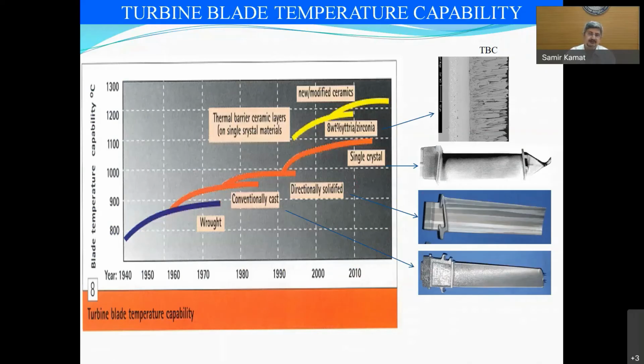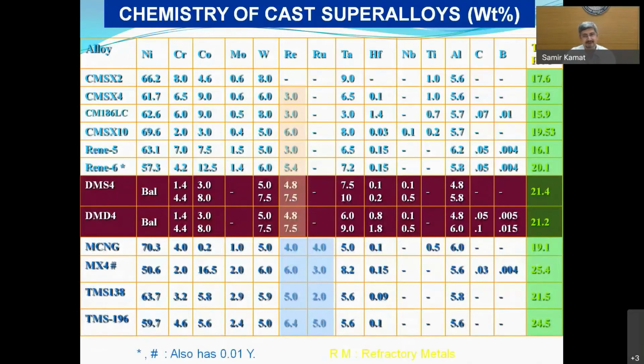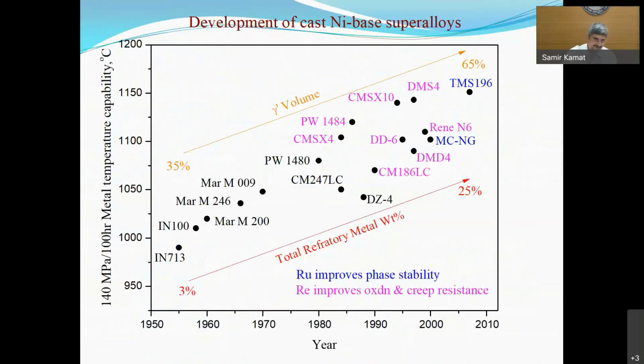In the late 90s, early 2000, DMRL also thought that for future requirement, we should also develop third generation nickel-based superalloys. Third generation alloys are alloys where you have rhenium additions of about 6 to 7%, which gives much higher temperature capability. So DMRL took up development of both a single crystal alloy and a directionally solidified alloy. And DMRL was successful in developing these alloys at lab scale. Now, if you look at the temperature capability, the DMRL developed alloys, that is the directionally solidified alloy as well as the single crystal alloy, have very good properties with respect to what is available globally.